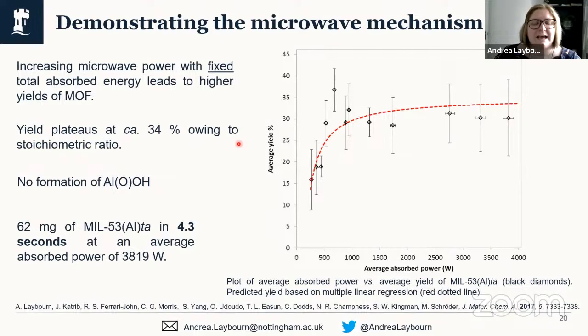And the reason for this is due to the stoichiometric ratio that we were using within our reactor. And this is related to the penetration depth of the microwaves within this reaction mixture. So we wanted to ensure that we were working at concentrations where you wouldn't get large differences between the heating at the outside of the vessel compared to the center of the vessel. So we were aiming for a more homogeneous delivery of that energy with specific components heating within it.